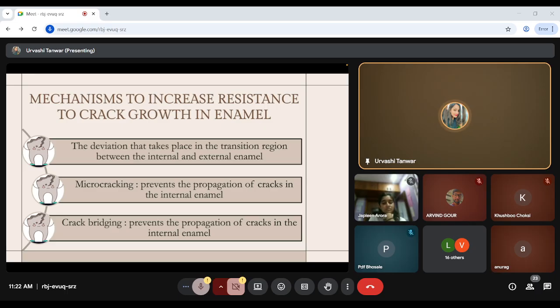This is what is going on in the enamel. The deviation that takes place in the transition region between the internal and external enamel. So basically, in the external enamel, the enamel prisms are relatively straight, and the cracks extend along these prisms. While in the internal enamel, the cracks meet oblique prisms, which cause their deviation. The next is microcracking, which prevents the propagation of cracks in the internal enamel. Now, microcracking occurs in front of a growing crack and it slows down the main crack by reducing the intensity of the local stress by dividing the crack.